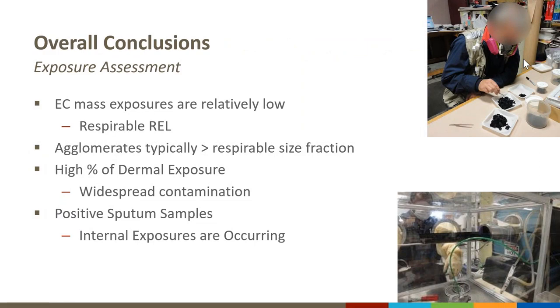So the overall conclusions from the exposure assessment were that elemental carbon mass exposures were relatively low, with only 7% of the samples being over the NIOSH respirable REL of 1 microgram per cubic meter. The material typically agglomerates greater than the respirable size fraction, most likely landing within the thoracic or inhalable size fractions. There was a high percent of dermal exposures that we saw between participants, and this was indicative of widespread contamination within most of the facilities that we visited. And then the positive sputum samples that we found let us know that internal exposures are occurring either through inhalation or ingestion. So I will turn it back over to Mary.